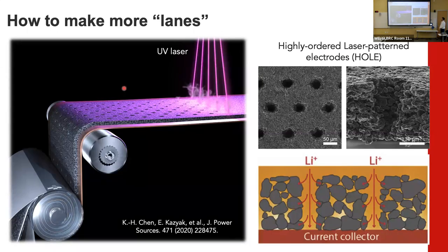So we use a UV laser in this case. It's roll-to-roll compatible. Pretty low cost. There's actually a startup company that we spun out that's trying to make this happen for actual batteries, but we're using a UV laser to cut many of these little holes that, in theory, should let the lithium ions go in faster.